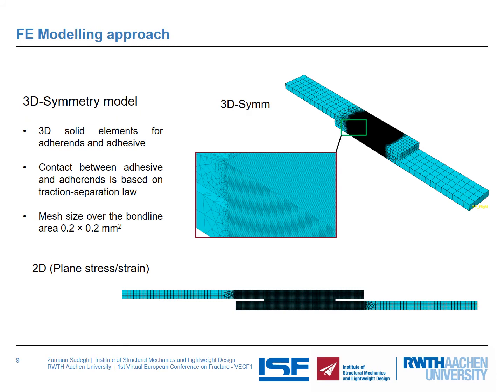As you can see, different FE modeling techniques were developed. First of all, a 3D symmetric model was developed, and also a 2D approach in two different forms, plane stress and plane strain, was considered. The contact between the adhesive and the adherent was modeled with the help of the traction separation law, and the mesh size over the bond line area was 0.2 by 0.2 millimeter.